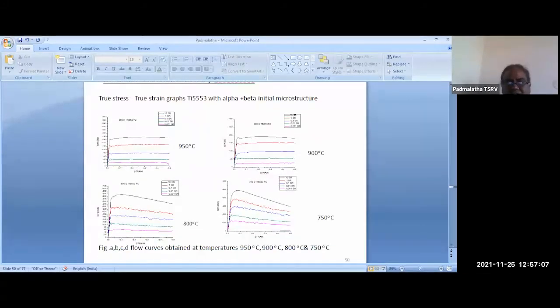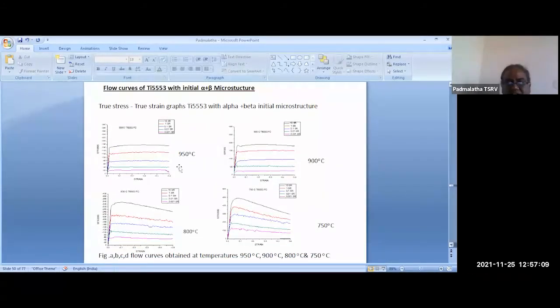So these are the flow curves generated by the machine at different temperatures and different strain rates. The red, black and blue colors are different strain rates. From all the curves, we can see that as we increase the strain rate, the flow stress increases. The black color is 10 per second. And also we can see that as the temperature is increased, the flow stress decreases. Those are the two major points, which are obvious.